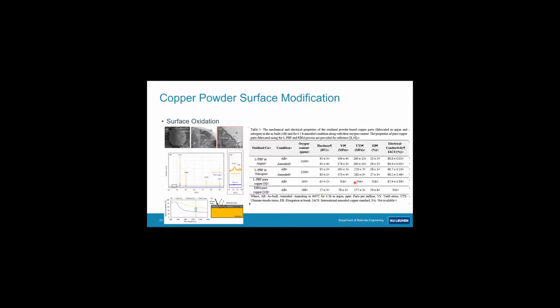And yeah, so we are still talking about yield strengths which are about double of pure copper, and an elongation at break which was about half the one of pure copper, which you expect. For example, this is an EBM pure copper result.